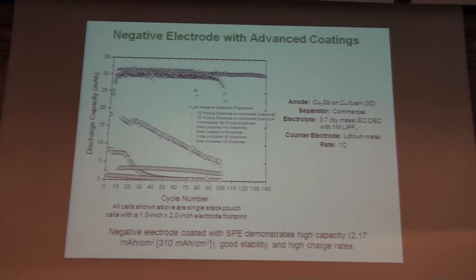But now if you go to 3 dimensions, the 3D foam, you see a dramatic improvement in the capacity, but you see that the cycle life is still pretty poor. If we coat now with some of our advanced coatings, you see the discharge capacity is high, and with our most advanced coatings, our recent coatings, the cycle life stays very good. So again, the technology that came out of my academic group is the plating of this anode material, but then in the company we've developed coatings that are really geared toward some of the practical aspects of how you'd actually want to use a battery.